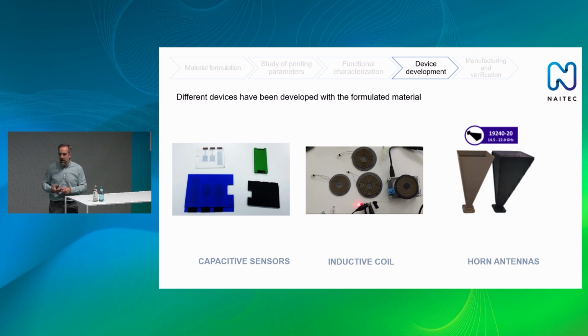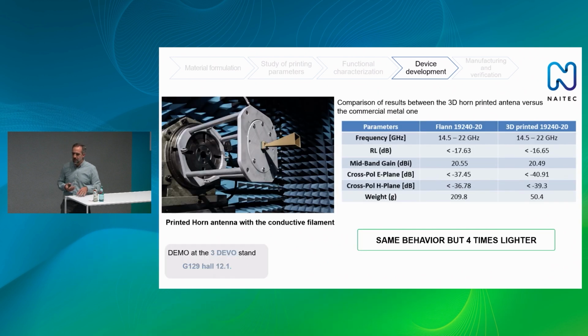Continuing with the characterization, we fabricated some demonstrators to see that this filament is actually functional. So we have fabricated a lot of capacitive sensors, integrated into different pieces. Also, of course, tracks for circuits. We have also printed inductive coils, and you can see the red LED is lit up with energy that is transferred non-contact with a contactless charging system, and we are capable of receiving enough energy from this 3D printed coil to light up the LED. And also we have printed horn antennas with FDM and our filament, and we have characterized this in an anechoic chamber.